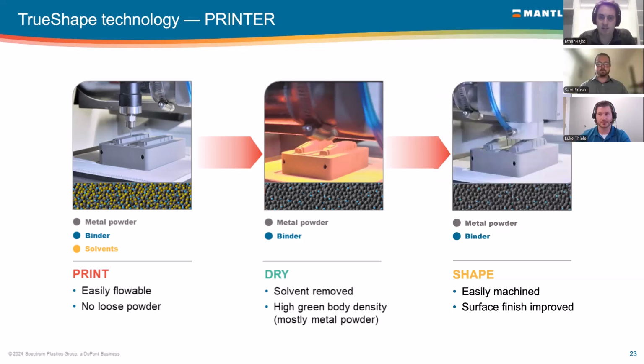The next step of the process is to dry this material. We're just doing this with heat. A heat lamp comes over the layer, and it removes the solvent out of the part. It firms it up a little bit and improves the green body density. So we go from this flowable, toothpaste-like material to something more like a dense foam.